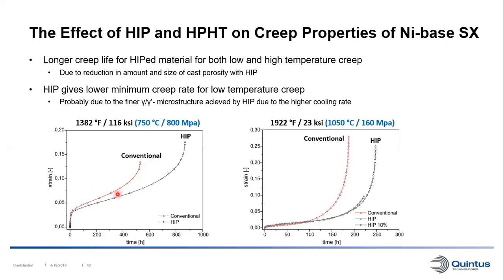We can also see, looking at this graph, that the HIP and combined HIP and heat-treated variants have a lower minimum creep rate than the conventionally treated material. And this is thought to be due to the finer gamma prime microstructure achieved by the higher cooling rate in the HIP.